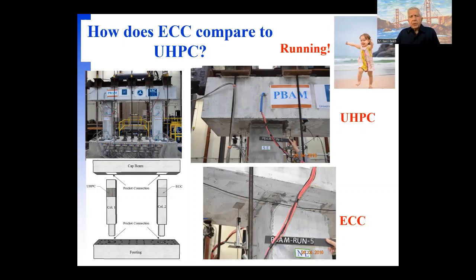So if you look at the pictures on the right side, the upper one is for UHPC and the lower ones is for ECC. The damage in the plastic hinge was relatively low in both cases. However, if you look carefully, you notice that for the UHPC, the damage extended into the cap beam. And that's a no-no in seismic design of bridges. We do not want any damage in the connection or extended into the cap beam.